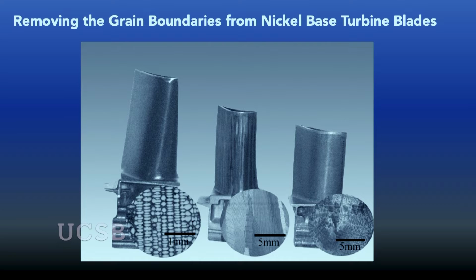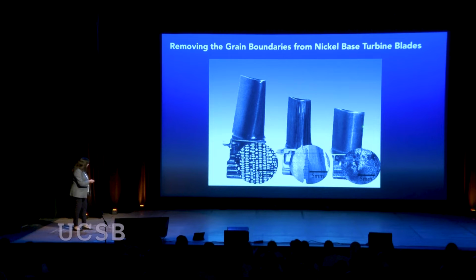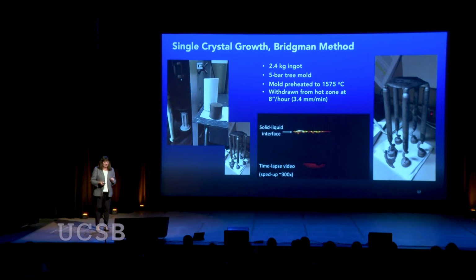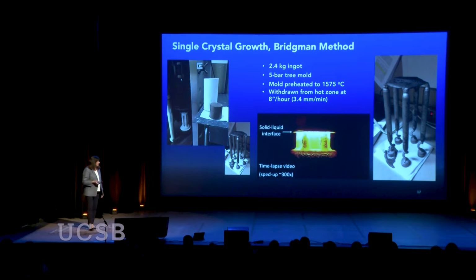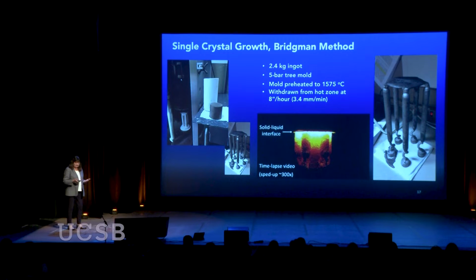And so there was a lot of effort that went into that, and it's a little bit hard to see here, I think, but this blade is polycrystal, billions of grains. This one only has grains running up and down because it's the ones that are transverse to the axis that accumulate the damage. And this one is a full single crystal. And now about 95% of the blades produced for aircraft engines are indeed single crystals. Now, it's not easy to do this. This is one of the things that we do research on, and I have for many years. This gives you an overview of how you would grow a single crystal.